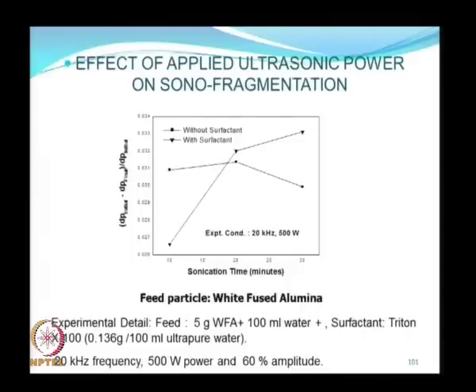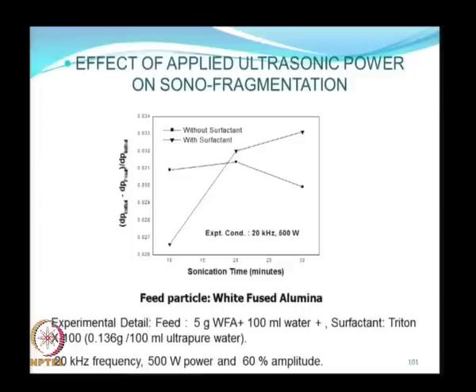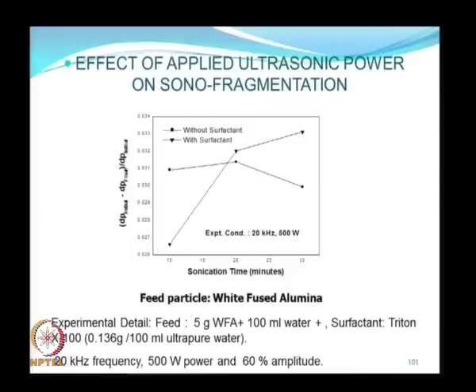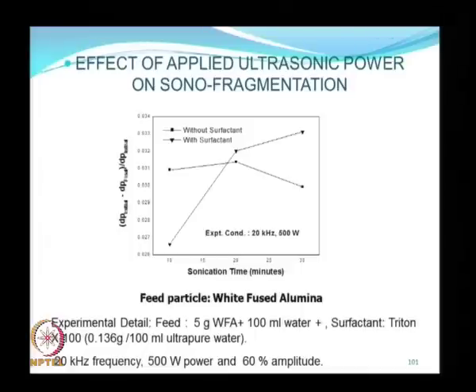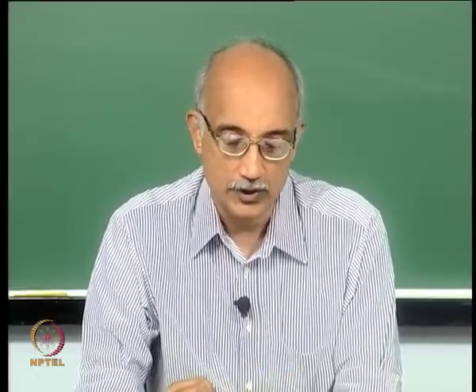Here, we are plotting time versus size reduction efficiency. As the time increases, the reduction in particle size keeps increasing, particularly when you use a surfactant. The use of a surfactant is very critical for two reasons. One is that the surfactant can coat on the nanoparticles that are produced and keep them from agglomerating. As we have discussed in earlier lectures, particle cohesion is a major phenomenon in nanoparticle suspensions, and by coating the particle with a suitable substance, you can essentially make the particles repel each other in suspension and keep them from agglomerating.